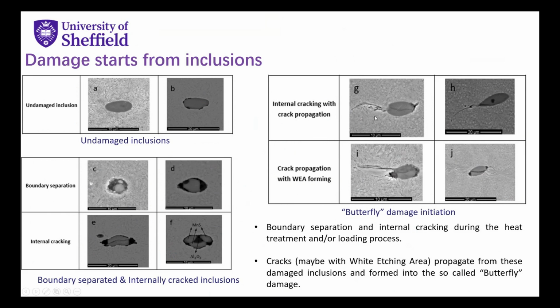Then we got some subsurface rolling contact fatigue cracks propagate from the tips of the inclusions. These are so-called butterfly damage. And sometimes we can also observe some white etching areas around these butterfly cracks. These white etching areas are a change of the steel structure from martensite to ferrite, and it makes the material become hardened and much more brittle, and it reduces the toughness of the structure and accelerates the crack propagation here.